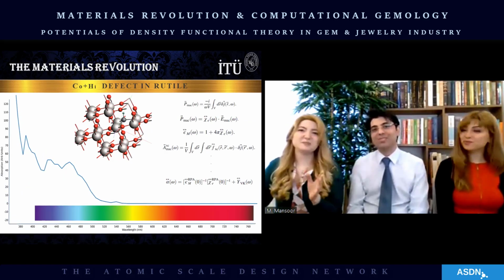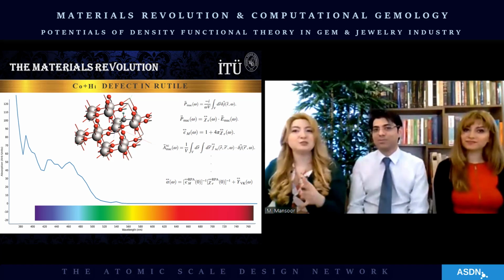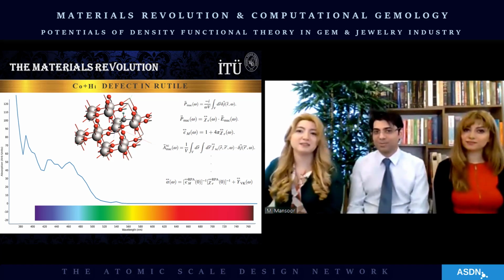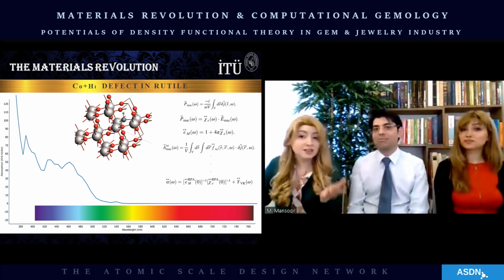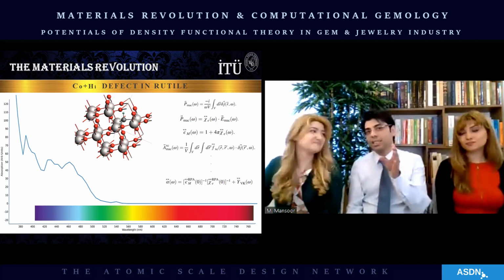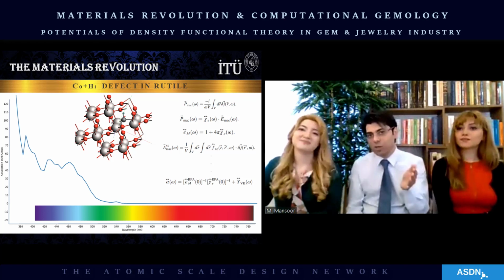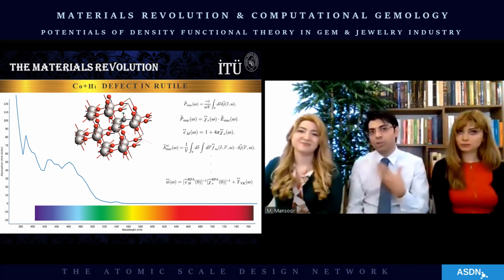So the UV visible spectra which emerges as a result of this defect was calculated using state-of-the-art time-dependent current density functional theory, using Professor Arjan Berger's kernel, which was developed only 6 years ago and includes electron-hole interactions. Yeah, so the dielectric function was evaluated using the macroscopic electric susceptibility through perturbation theory.